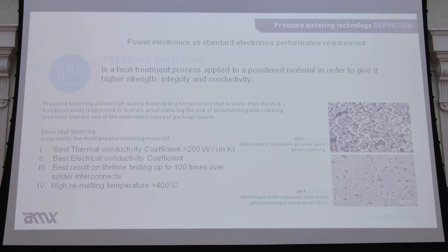What else? Thanks to this technology, you can have better thermal conductivity, and also a lower electrical resistivity. In addition to this, we have some data and analysis from the Fraunhofer Institute that show that also in terms of mechanical joint, this technique gives the component a higher lifetime because there is a certain ductility at micro scale. We have some studies, as I was mentioning before, that show that this technology can reach more than 100 times the lifetime of a standard reflow interconnection.